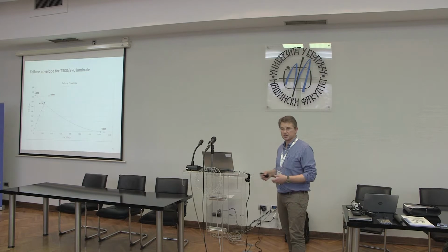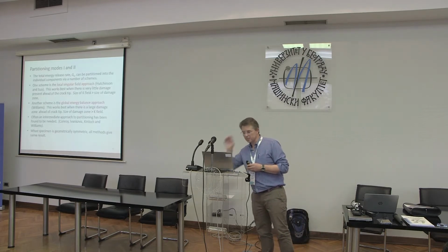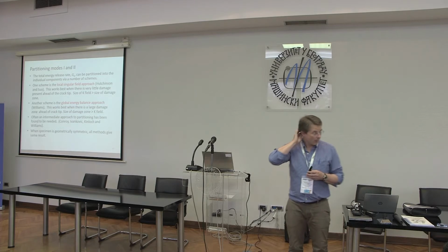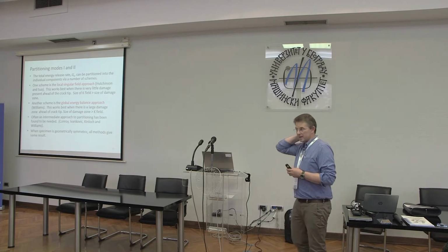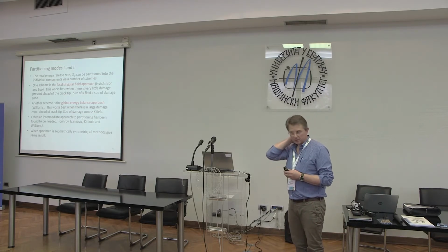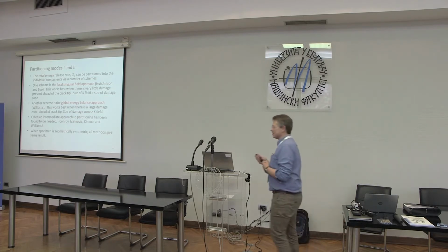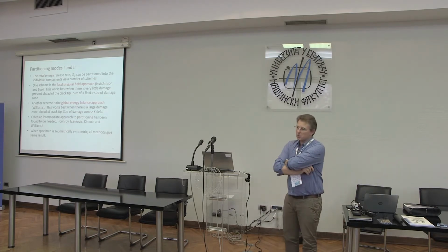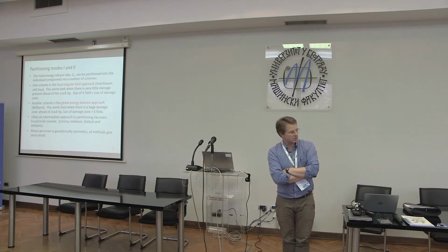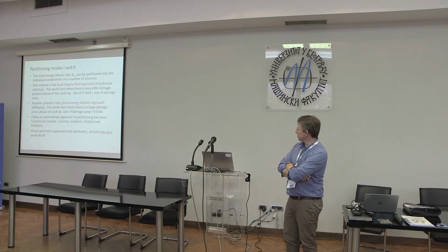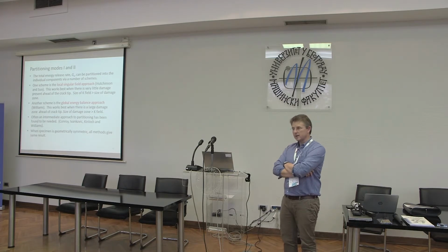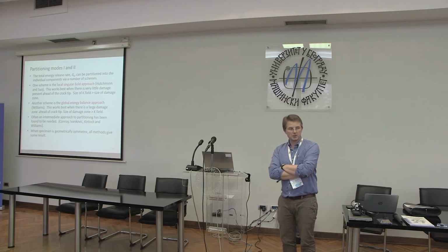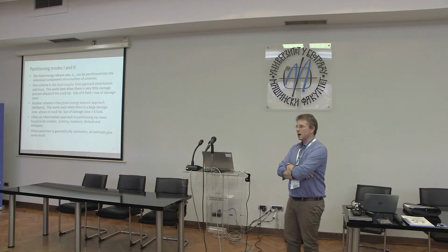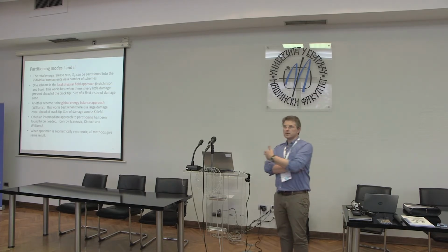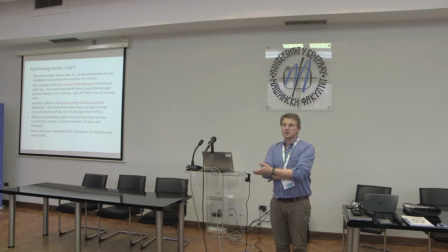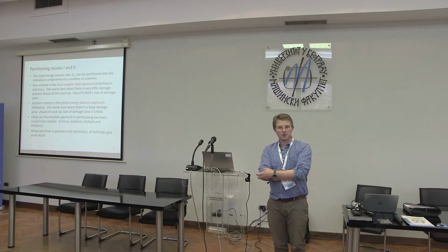because you're trying to take material out. So there's been quite a lot of discussion about partitioning accurately, and this is a complicated subject, and I could talk for 2 hours on it. Fortunately for you guys, I'm not going to. But the takeaway point really is that if you need to partition any of these energy release rates accurately, it is unfortunately a material specific problem. And what partitioning strategy will work for one material won't necessarily work for the next one.